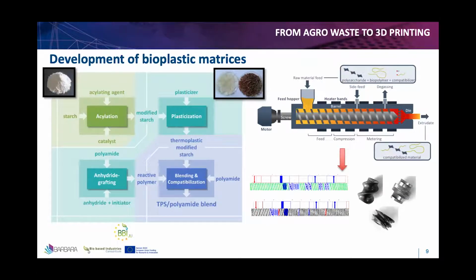The BARBARA materials were developed through an extrusion compounding process. The twin screw is comprised of small pieces called screw elements that are assembled in the shafts. In twin screw extruders, there are three main types of screw elements: the kneading blocks, reverse screws, and conveying screws, which basically permits to transport, mix, and control the shearing. The screw profile is a very important factor in extrusion processes and affects significantly the transport of the materials in the extruder.